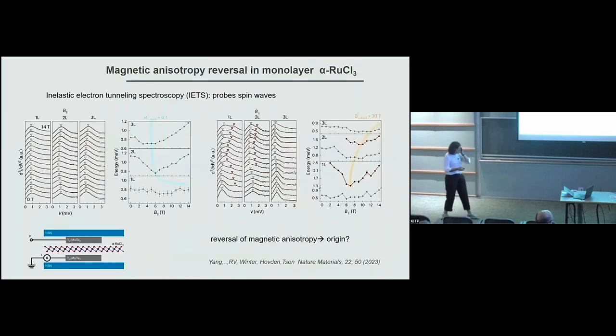So now, what the experiments from Adam showed is that he did different thicknesses of alpha ruthenium trichloride, and this is the first derivative of the conductance. Here I'm showing these peaks as a function of magnetic field. If you are in a 3-layer, you see what you expect: the zigzag long-range order is suppressed at about 6 to 7 Teslas, and then you enter the region that is partially polarized.